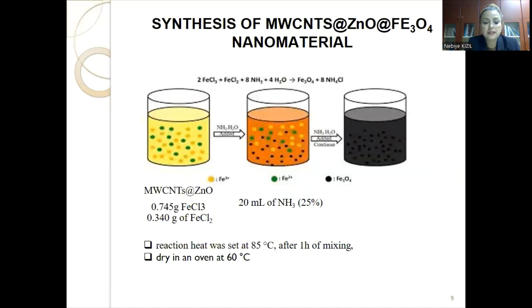Then we synthesized multiwall carbon nanotubes, magnetic multiwall carbon nanotubes with zinc oxide. In order to do this, iron 3 chloride and iron 2 chloride were added slowly to the obtained nanomaterials. After 1 hour of mixing for reaction at 85 centigrade degrees, the mixture was cooled and washed with water and acetone, and finally dried in an oven at 60 centigrade degrees.